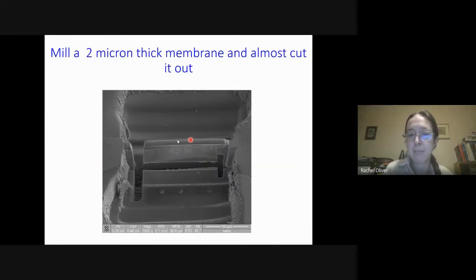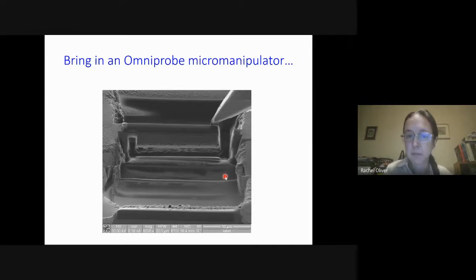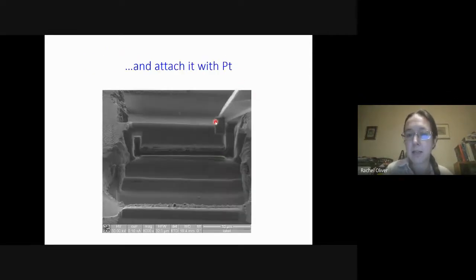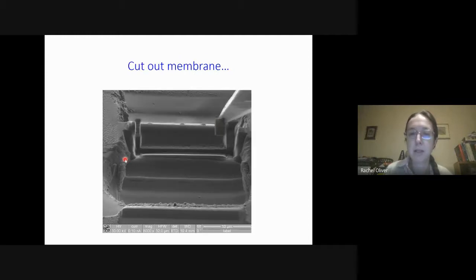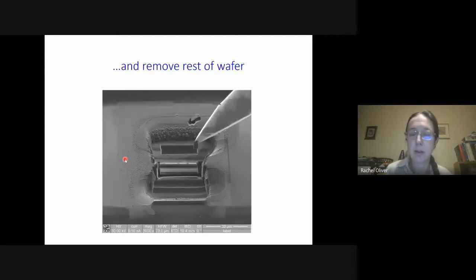Here's one of our membranes from our quantum well wafer. And you can see we've also used the ion beam to cut down here and across, making this sort of gate structure, which is ready to take out of the wafer. We bring in a needle, and you can literally make sticking tape out of the available platinum in the FIB to tape your sample to the needle, and then we cut it out from the wafer and bring it away.